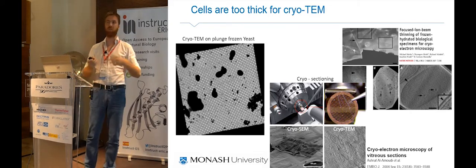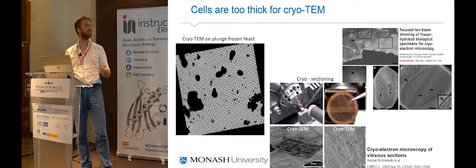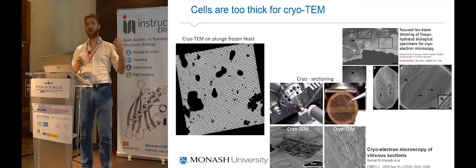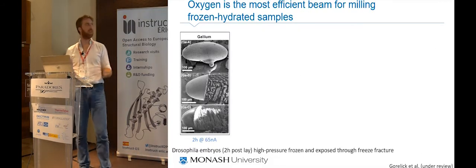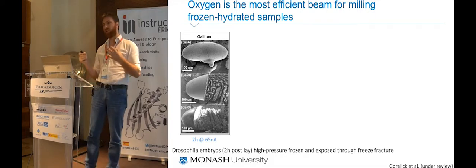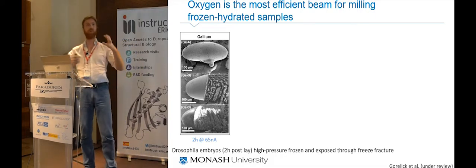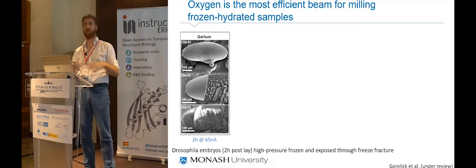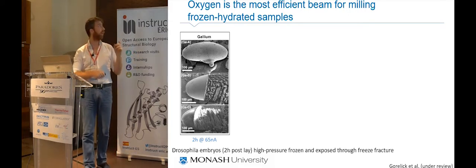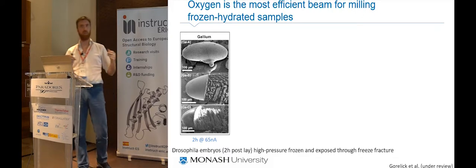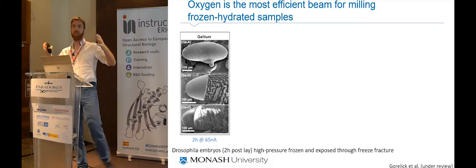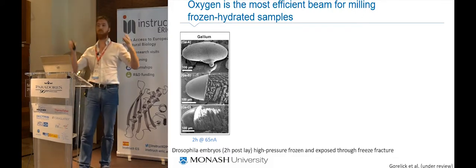So we thought, okay, we were so fast in cutting all this resin, and it was cutting so nicely with oxygen, for example. We could actually try and see what happens. Let's do something massive. We take a Drosophila embryo, we high pressure freeze it. In this case, we just exposed it by freeze fracturing so that we could take pretty pictures. But let's see how fast we can obliterate part of it, so we can measure what the removal rate is.